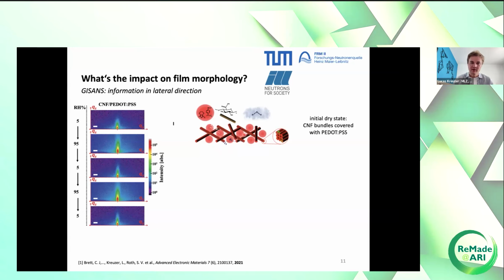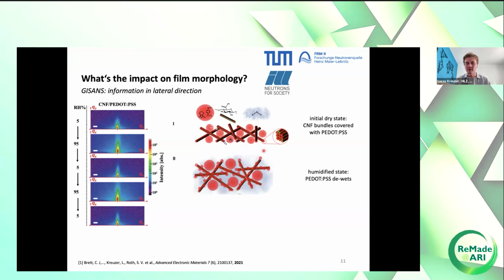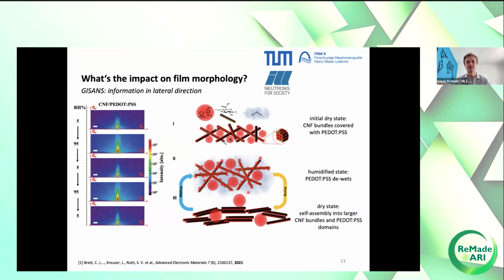Now, when you humidify the entire system, water moves into the film. We saw this with QENS, we saw this with reflectometry. And what we see here is that PEDOT:PSS dewets from the CNFs and forms smaller clusters along these fibrils. And in between, we still have these PEDOT:PSS rich domains. Now, if we dry the entire system, interestingly, we don't go back to this first state, but we enter a third state, namely this state here.